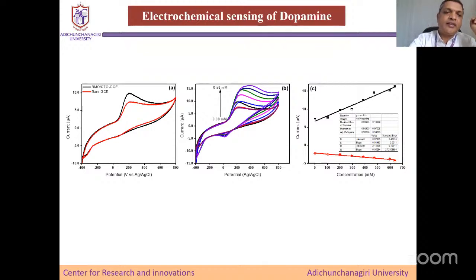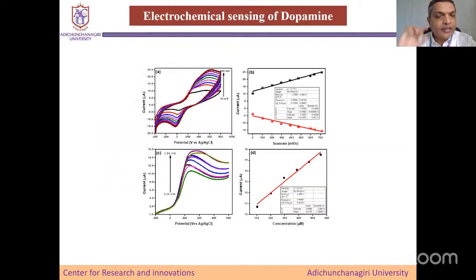So this is the cyclic voltammogram of the nanocomposite on the glassy carbon electrode, and also the bare glassy carbon. There is a difference, and you can see here the scan rate. As the scan rate increases, and as the concentration increases, there's a change in the current. And again, the plot of concentration versus current gives the limit of detection. And this is again linear.